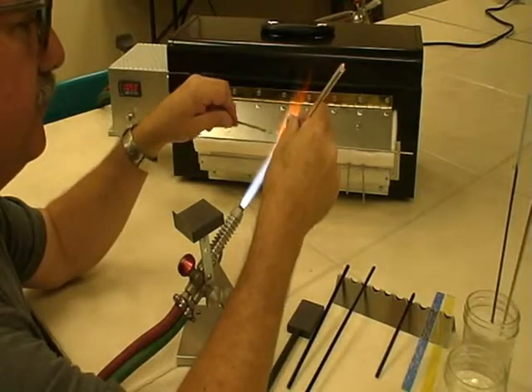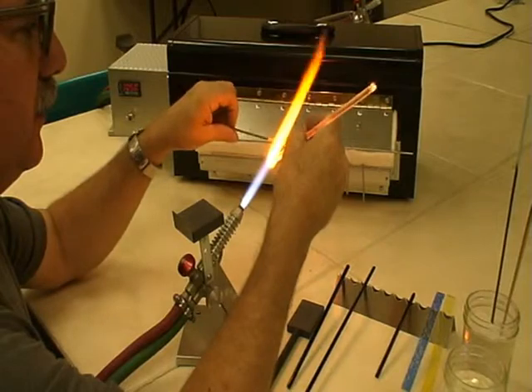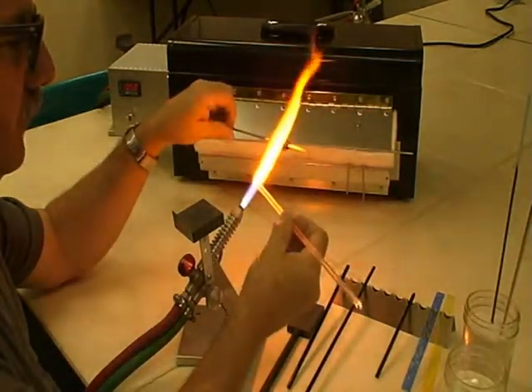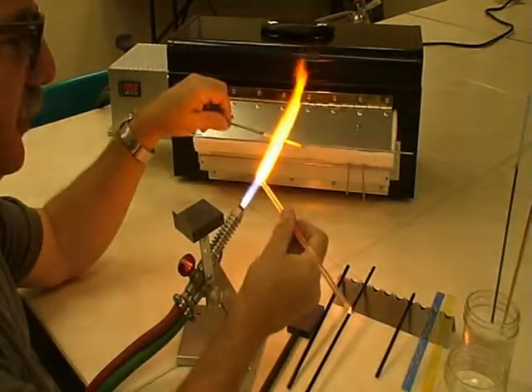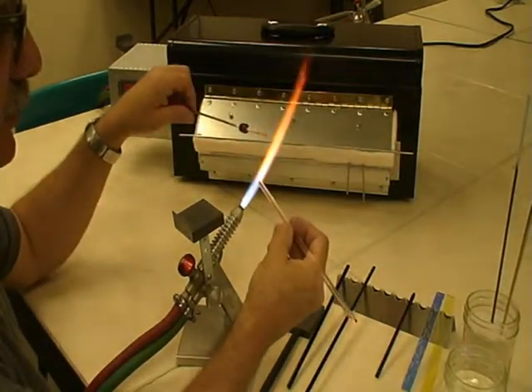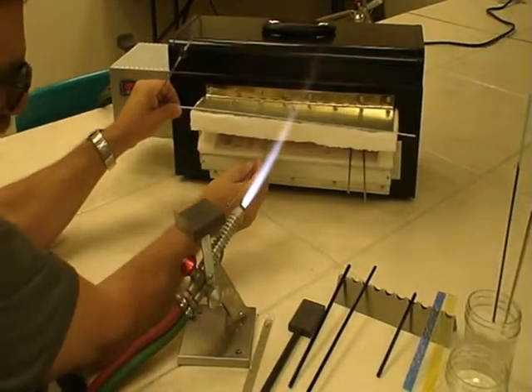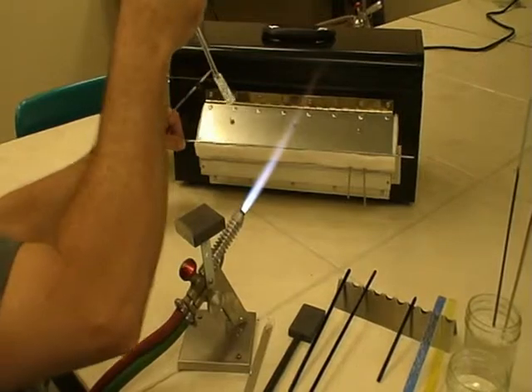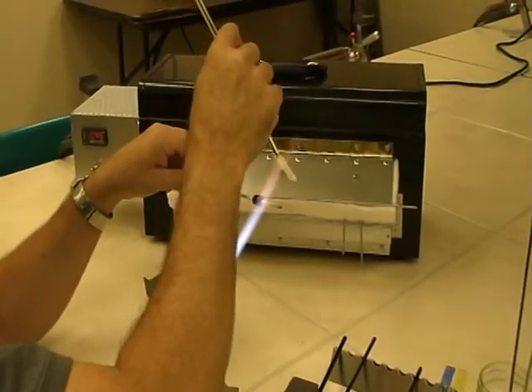On this next bead, I'm going to apply a piece of dichroic that I'm going to take out of my kiln to this bead that I've already made. I'm heating a clear glass rod. That's what I'm going to use for my putty. I'm going to go into my bead annealing kiln and putty up a strip of glass that's heating in there at 1050 degrees. At 1050, it heats it enough so that it won't thermal shock when I come to the flame. And yet any beads that I put into the kiln also will not be damaged. They won't slump or stick together at 1050.